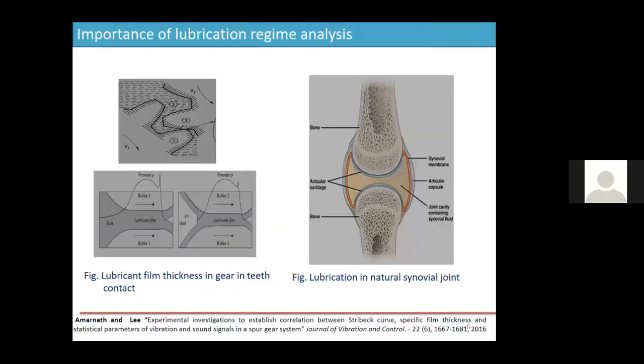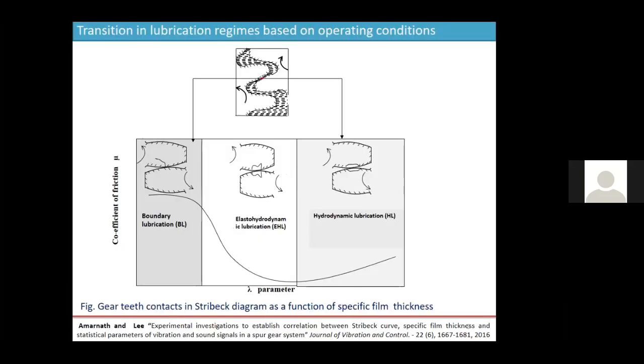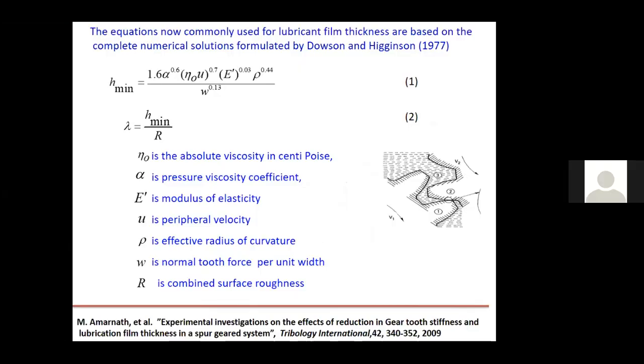We are supposed to analyze the lubrication regime, whether it is hydrodynamic or elasto-hydrodynamic or mixed, etc. For that purpose, we can use an empirical equation developed by Dowson and Higginson. This equation is used to estimate lubricant film thickness. Lubricant film thickness can be estimated by considering viscosity, peripheral velocity, modulus of elasticity, and geometry and loading conditions. So radius, modulus of elasticity, viscosity, speed, and load. With these parameters, you will be able to get H minimum, the minimum film thickness.